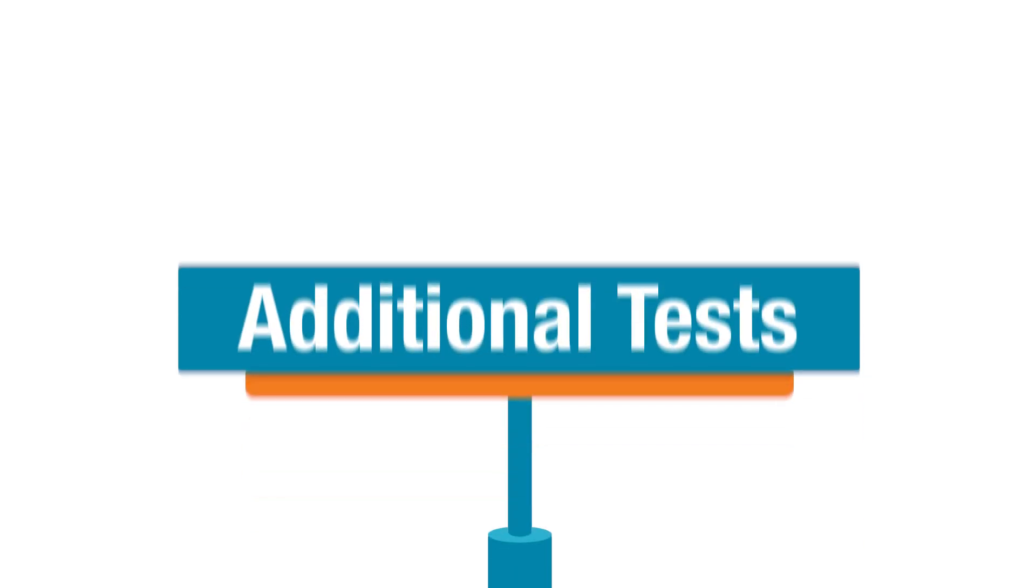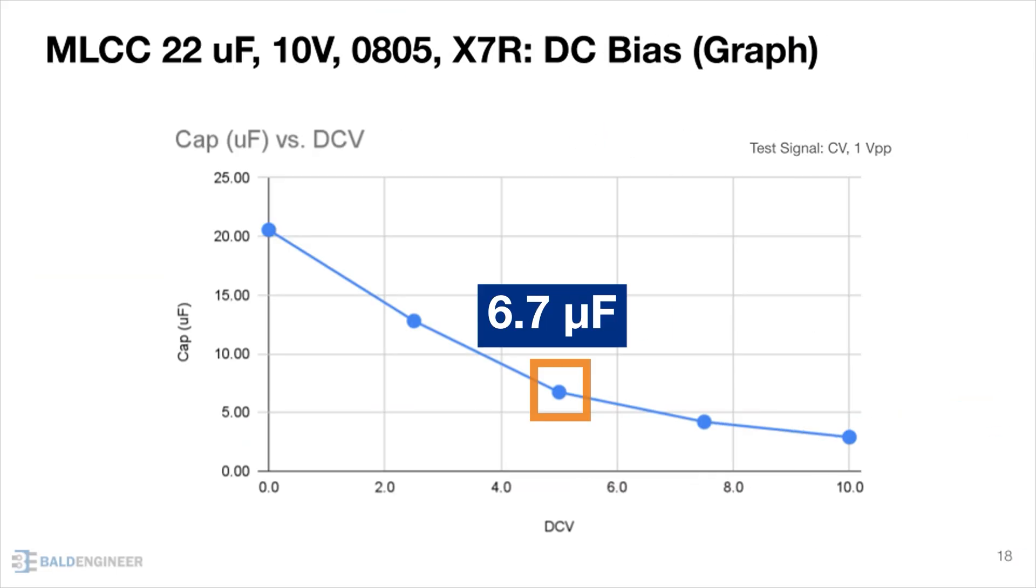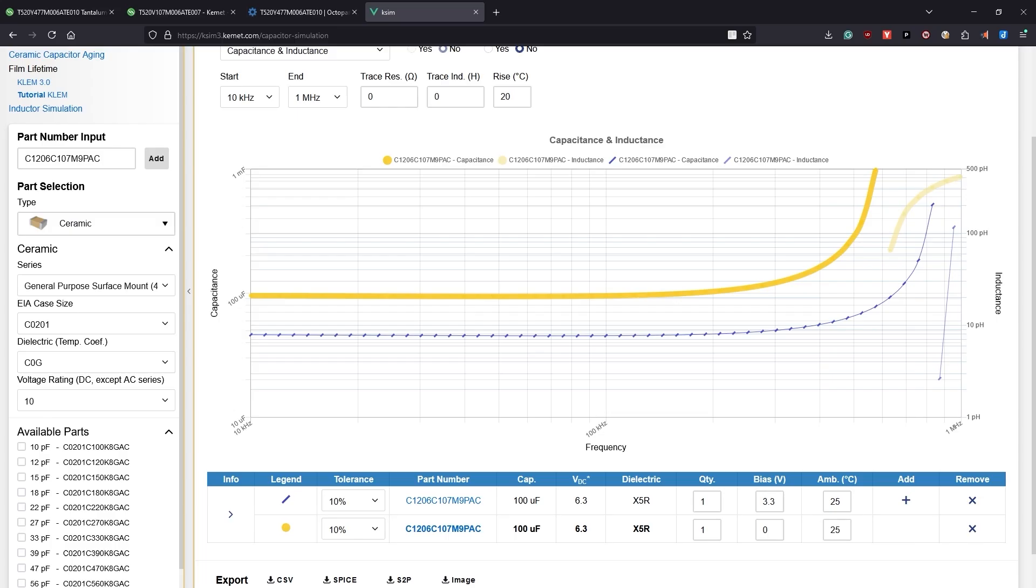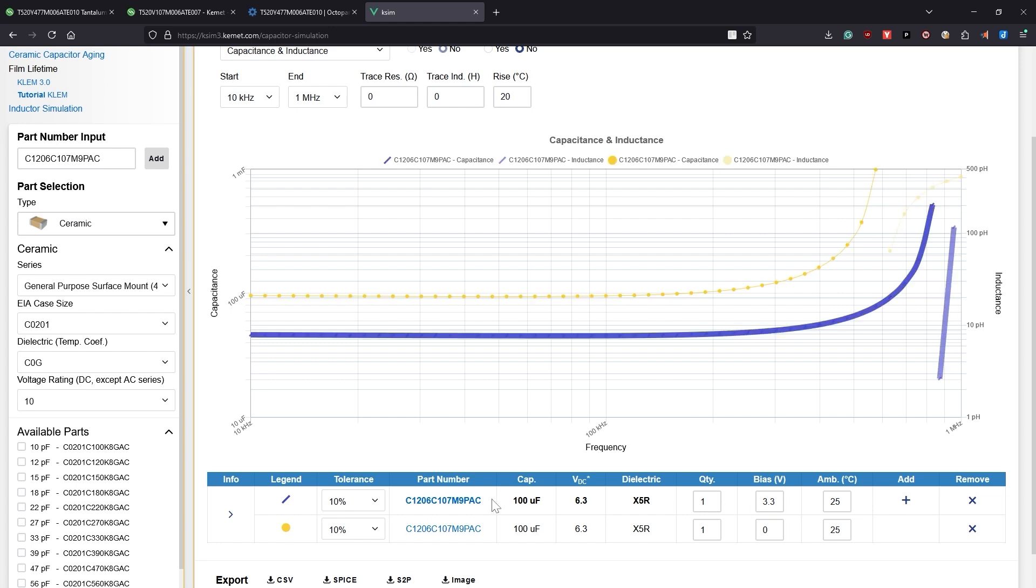Next, let's cover a few more measurements. Remember, I said ceramic capacitors have a DC bias effect or voltage coefficient. This graph is from Kemet's KSIM. The yellow line is the MLCC with no DC voltage applied, and the blue line has the 3.3 volts of our supply's output. The 100 microfarad capacitor dropped to 46 microfarads, or about half.